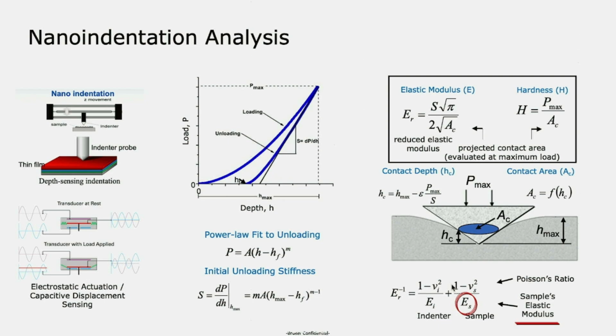We are using a very high accuracy transducer, and this transducer can record the applied force and the displacement during the indentation procedure. So this is the diamond probe. The diamond probe has a known shape, and we can apply the force with our transducer and indent into the material and pull out from the material.